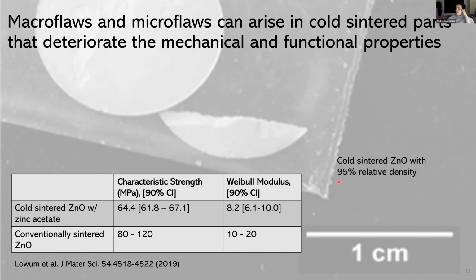But you see that even though it had a 95% relative density, which is considered quite good for ceramics, I know for those of you that work in metals, that's probably like, no, that sounds quite low. 95% is actually quite reasonable. But when we look at the properties, the sample actually broke quite easily just in our hands. Now, this is also reflected in the literature when you look at the characteristic strength of parts that were cold sintered versus conventionally sintered. You can see that the characteristic strength drops quite significantly, as does the Weibull modulus, so we have more of that variation, which is not exactly desirable.